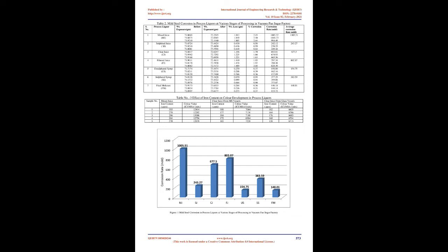Corrosion in sulfured syrup. In a sugar factory, prior to crystallization, syrup obtained from evaporators, i.e. unsulfured syrup, is bleached by passing SO2 gas, and in the process the pH of sulfured syrup is maintained around 5.0 to 5.2. The corrosion rates of mild steel in sulfured syrup were found to be around 375 mdd, which are almost 125% higher than the corrosion rate of mild steel in unsulfured syrup. Since, as evident from Table 1, except for pH, there is no material change from unsulfured syrup, it may be inferred that corrosion rate has increased owing to lower pH values.